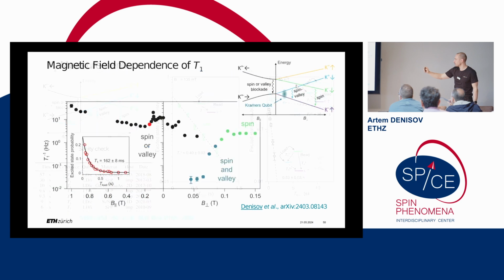All right. Also, as a function of magnetic field, we can nicely see how, as we go lower in magnetic field over the crossing point, meaning we go from the spin blockade to spin and valley blockade, the T1 time just really sharply drops. There are also these black points, which correspond to relaxation requiring either a spin or valley flip, which we cannot really distinguish. I'm not going to talk about it. We don't really understand some of the physics around these hotspots. But one point I want to make here is that at zero magnetic field, we still measure 100 milliseconds of T1 with a 99.99% electrical readout fidelity, meaning that in principle you can make a zero field spin or valley qubit if you know how to rotate it. Zero magnetic field.